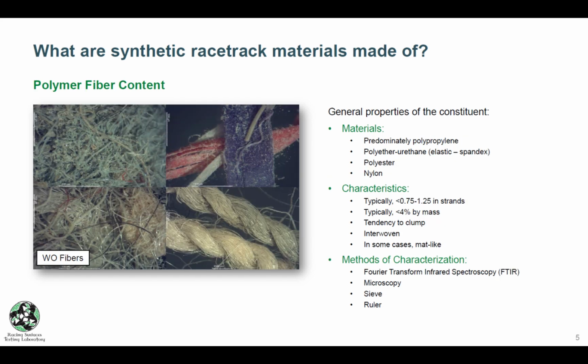Fiber content varies quite dramatically from track to track, but we are able to test and identify what fiber is being used. We see a lot of polypropylene. We see a lot of the elastic, the spandex, maybe polyester, the nylons. Generally, the fiber lengths are going to be about 3/4 of an inch to 1.25 inches, and we're going to see about 4% or less of the total fiber content present in a synthetic racetrack. Again, we can test for this.